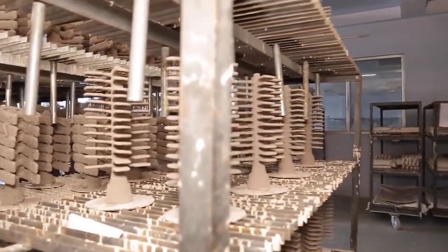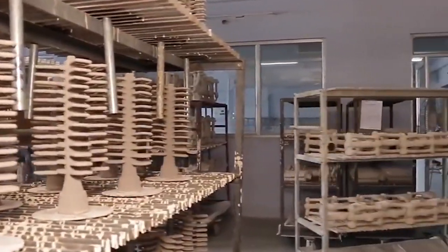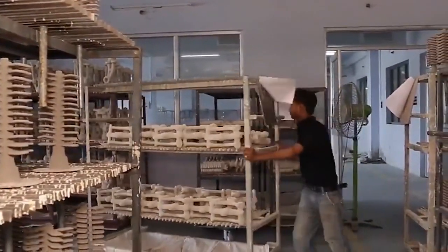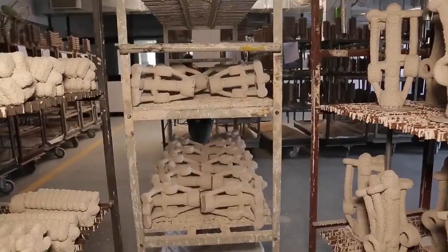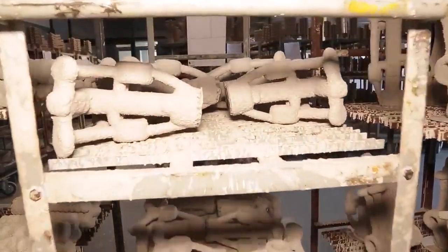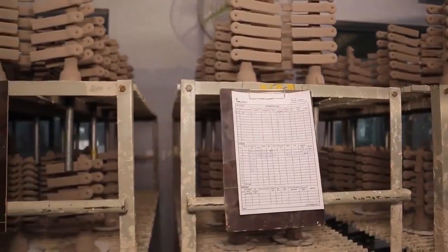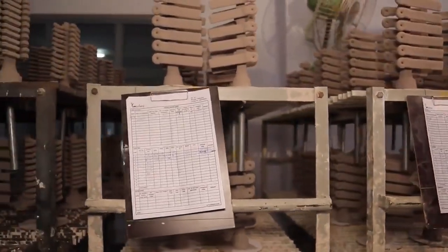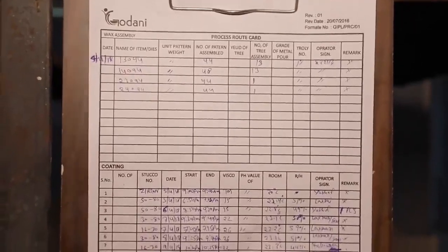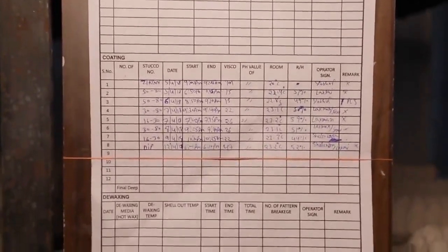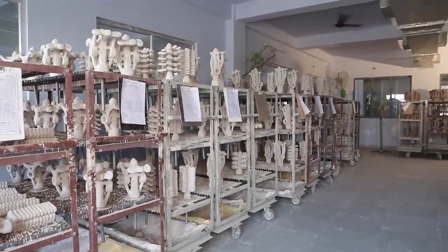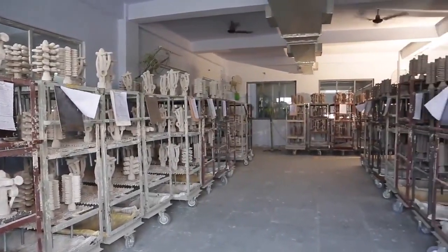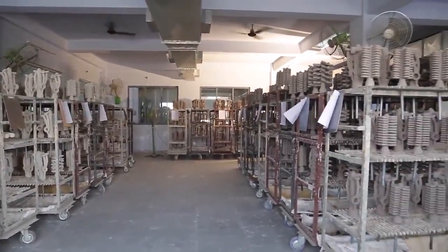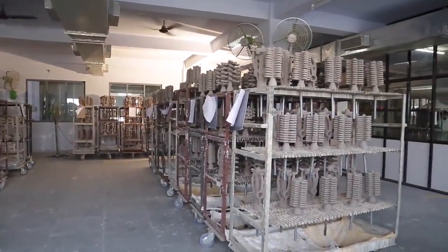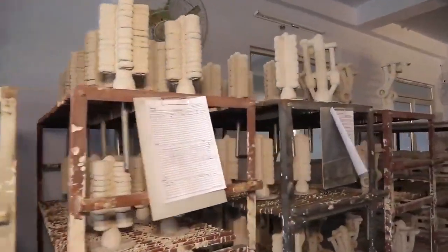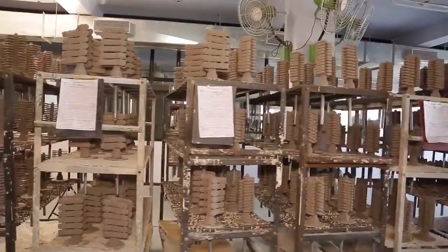Typically, a minimum of 3/8 inch thick shell is required to achieve a green strength capable of withstanding the pressure of wax expansion during dewax. Since investment shells are cast unsupported, it is also necessary to have a fired strength capable of holding the weight of the metal cast, another consideration for determining the shell thickness. To minimize shell cracks from wax expansion, it is absolutely necessary to achieve dewax temperature in a very few seconds. As the wax melts, it exits the shell through the runner or sprue system of the assembly.